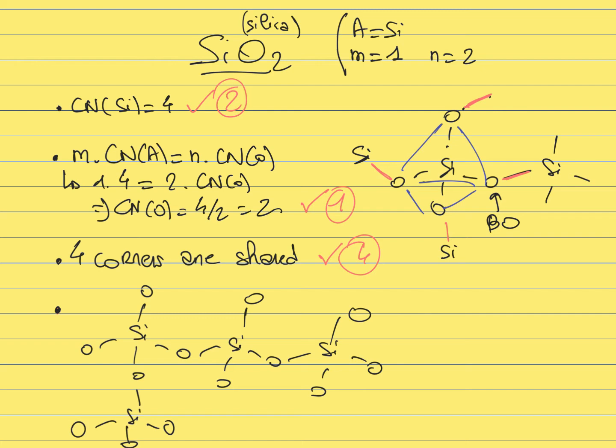And since this is true, then it means that the third Zachariasen rule is satisfied. So in that case, we find that all the 4 Zachariasen rules are satisfied, it means that silica, as expected, is a good glass former. It has a good glass forming ability since it satisfies all those 4 rules of Zachariasen.